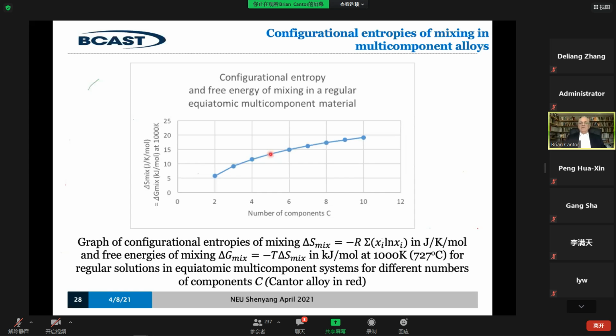It goes up not too fast, but if you get up to 5 components, the entropy in joules per K per mole is about 14. Sorry, it's 15 at 6 components. At 5 components it is about 14 joules per K per mole. And if you turn that into free energy at 1,000 degrees, it's about the same number, 14 or 15 kilojoules per mole at 1,000 degrees. So that's where we are.